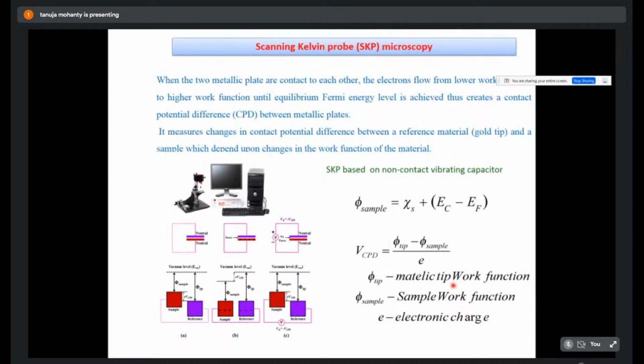We have used, and I have used the word optoelectronic. That optoelectronic means actually we do the electronic study, means the change in the variation on the surface because of the Kelvin probe analysis. So that is the scanning Kelvin probe. Scanning Kelvin probe is a unit which measures the work function of the material. So work function of the material is related to the binding energy, and that phi sample is related to the conducting band energy and the Fermi level energy. And actually we measure in terms of the VCPD.